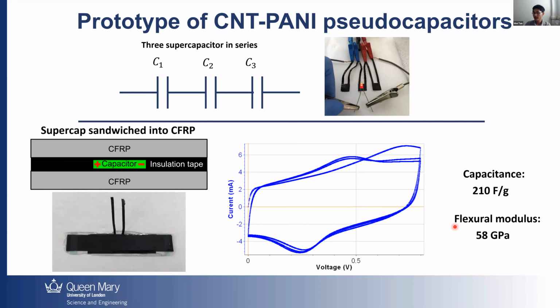And if you look at the flexural modulus, 58 gigapascal, that's mainly contributed by the unidirectional CFRPs. So as long as the capacitor does not degrade the mechanical properties, we think it's good. It still can do a lot of jobs. So if you want to scale up these things, you need to connect them in series or in parallel like the battery packs so that it can scale up. The good thing is it's like a thin laminate. You can put it on the surface, internal structure, or as the internal sandwich structure of the existing CFRP.